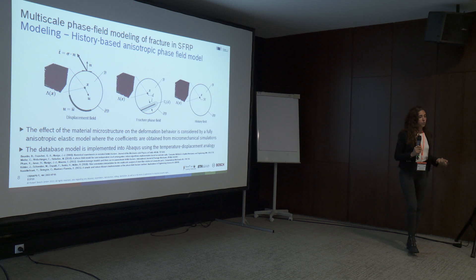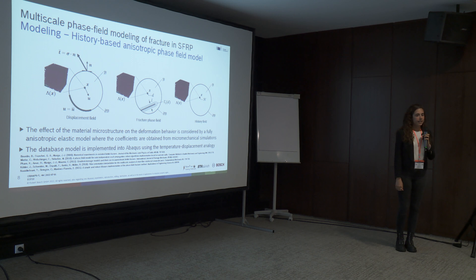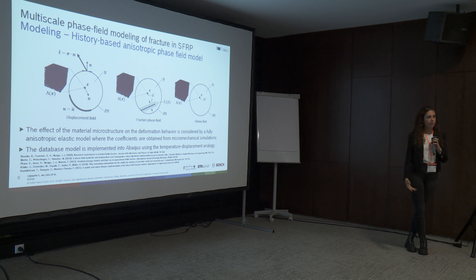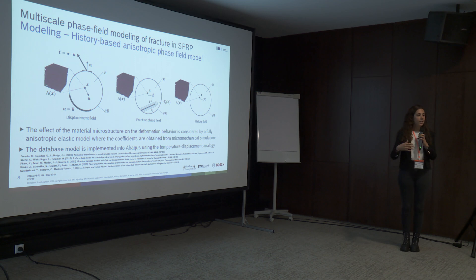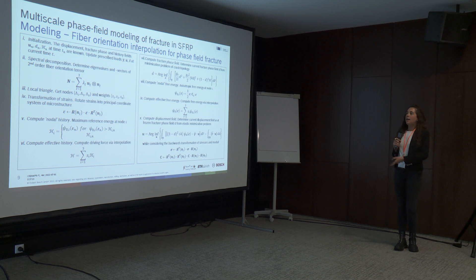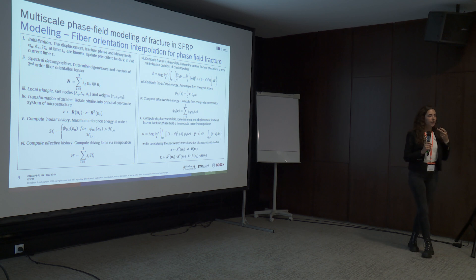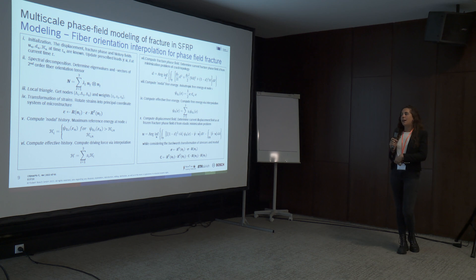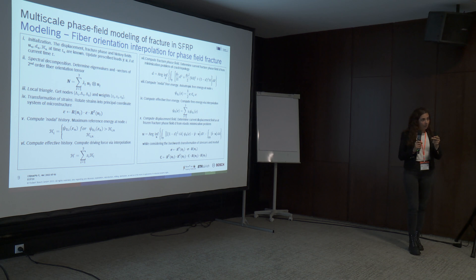We link this framework with phase field because we are interested in fracture. We use Emilio Martínez-Pañeda's UMAT, which takes advantage of the analogy between the heat transfer problem and the phase field problem. Specifically, we use displacement-temperature coupled elements — the C3D8T elements — so the temperature field carries the meaning of the damage field.